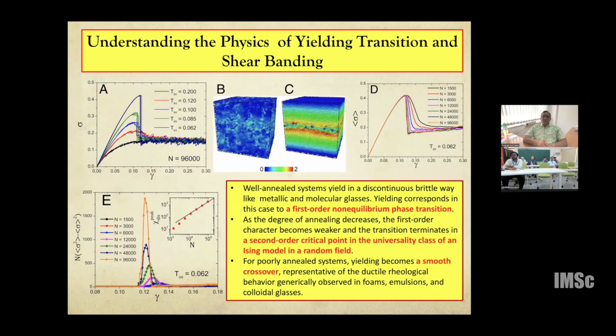So there are interesting proposals by the same group that this shear banding process in ultra stable glasses is a kind of first order non-equilibrium phase transition, which has been debated a lot in the literature, and it is not clear what it is. And it's also been claimed that when you change your annealing history, you are basically going through a phase diagram where you have a first order phase transition terminating at a second order critical point, and the physics is claimed to belong to the same universality class as the Ising model in a random field. As I said, these are theoretical developments that have been debated strongly, and there is no clear-cut answer yet.